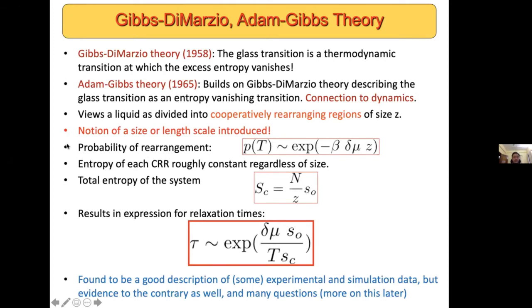Now, given what I said about the CRRs, for short, being sort of the minimum size for structural reorganization to occur, one can also make a plausible assumption, as Adam and Gibbs did, that regardless of what the size is, which varies as a function of temperature, the entropy content of a given CRR remains roughly the same. Therefore, if I look at the total entropy of the system, it's some number that's proportional to the number of CRRs I have. And therefore, it's inversely proportional to the size of the CRRs.